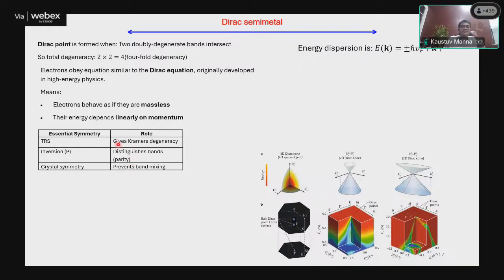So what are the essential ingredients we need to protect the Dirac semimetal? One is of course the time reversal symmetry. Time reversal symmetry must be protected, and as I explained previously, time reversal symmetry gives rise to Kramers degeneracy and spin-momentum locking also. Second, the new addition we are introducing here is that the crystal symmetry plays a very dominating role. A particular symmetry must now be protected, which is the inversion symmetry. The inversion symmetry induces parity in the system. I will be explaining how inversion symmetry introduces parity and what the implication of this is.